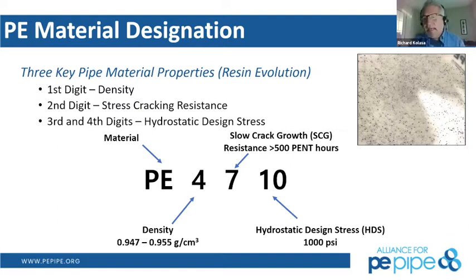It's to kind of give you an idea of having a reagent penetrate that amorphous area. So the kid going through the ball pit, if I stated that analogy, what you end up with is 1 hour of PENT is equal to 14.1 years of service life, according to Dr. Norman Brown, the inventor of the PENT test, which is the Pennsylvania Notch test. And it's a stress-related test over time that fails the product to understand what the resistance is of the slow crack growth failure mechanism. So that's what we're really looking at, that failure mechanism.